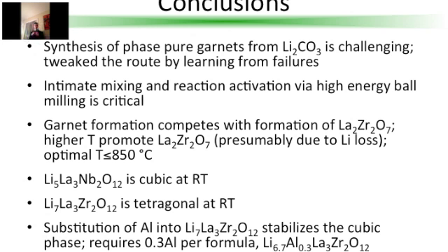I also was able to conclude that to actually synthesize the materials requires very intimate mixing. And to do this, you really need to use high energy ball milling to activate the reagents. If you just use a mortar and pestle and mix it by hand, it simply won't provide enough energy to the reagents to activate them.